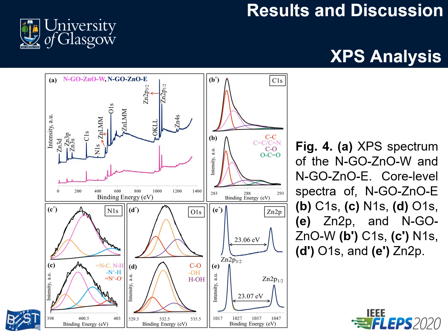The surface spectra of both nanomaterials were deconvoluted to figure out the mechanism of zinc oxide nanorod morphology and growth by understanding the individual oxidation state of each atom present in the system. C1s spectra showed the corresponding peaks of sp3 C, sp2 C, C-O and carbonate at their respective binding energies.